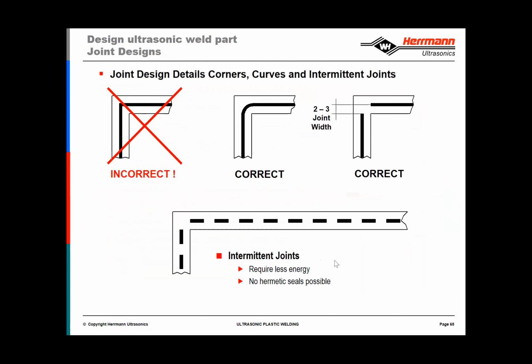When designing your parts and you have a corner that you have to negotiate around, we do not recommend that the energy director be squared off. The energy director should be radiused, or if it's just a mechanical bond that you're looking for, eliminating that corner or 90-degree shape is preferable. Reason being is that in the corner here, an overabundance of melt is created, and that overabundance of melt can sometimes cause you to underweld the part, or if you do overweld the part, then that overabundance of flash usually doesn't have anywhere to go, so it is visible on the outside of the part.